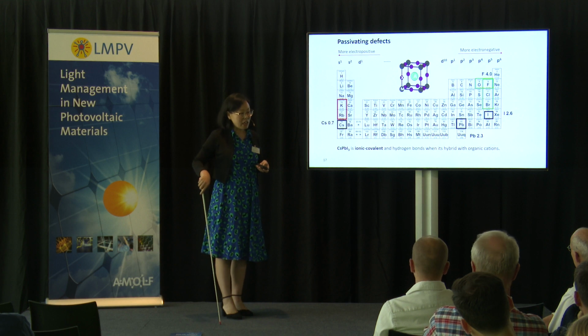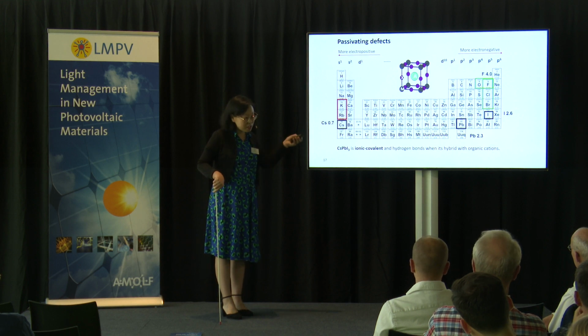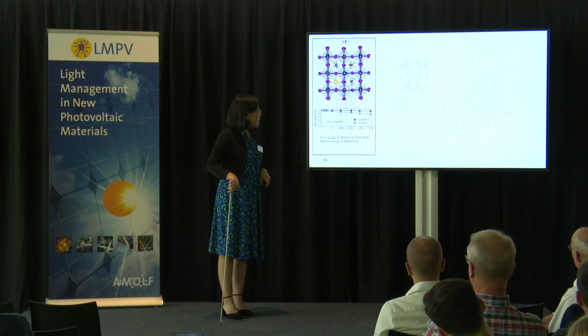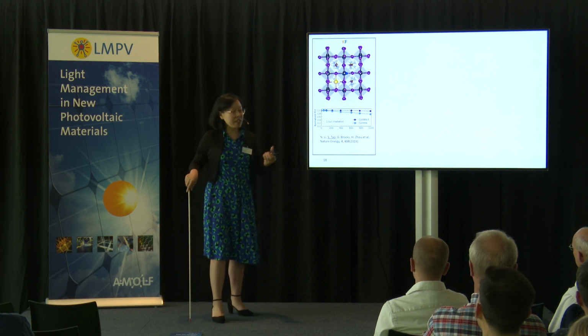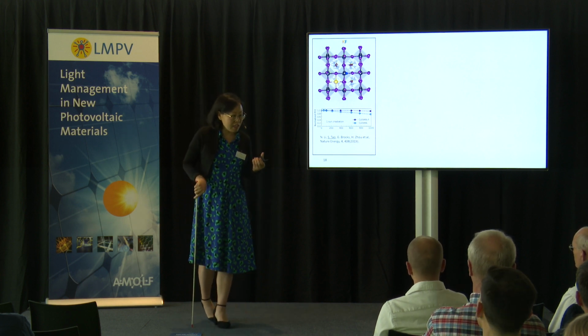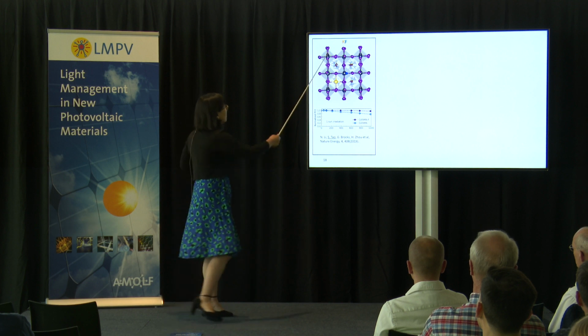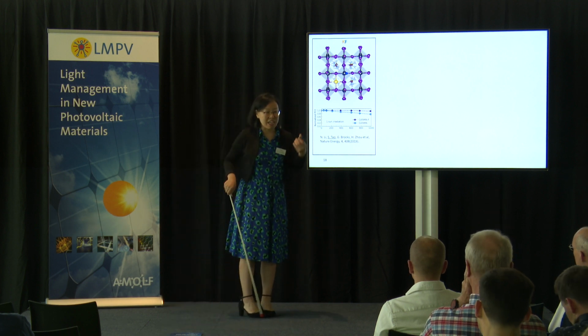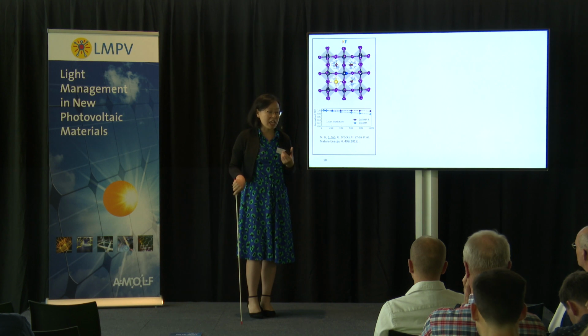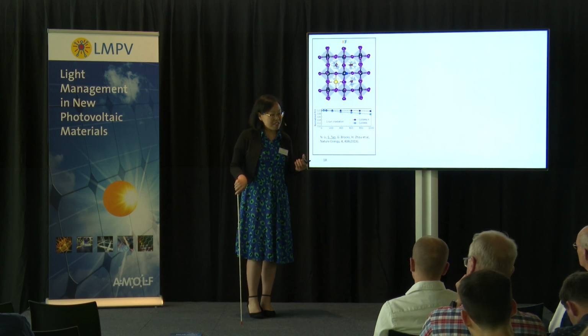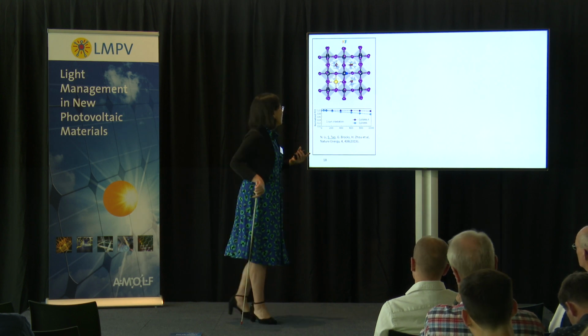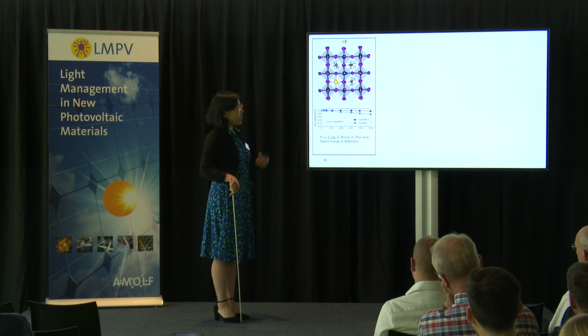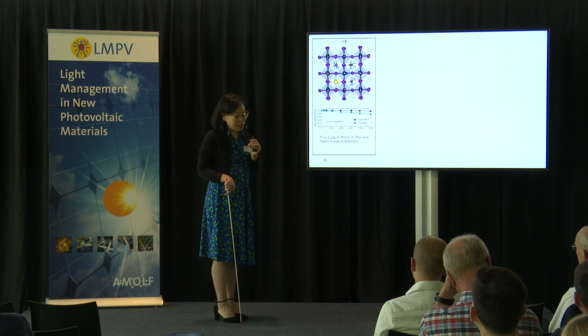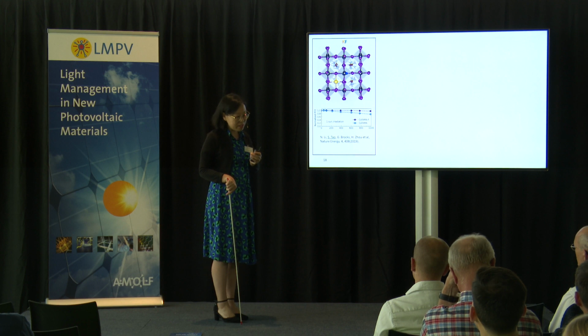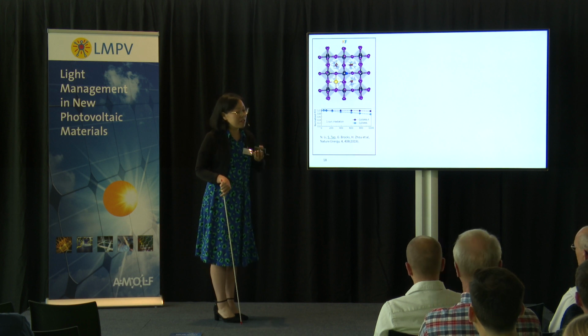And indeed, I'm going to show you a few examples of how we did this. The first case is incorporating a little bit of fluoride in the cells. Fluoride is the smallest atom, except hydrogen, of course, and has the most electronegativity, and therefore, when we make the cells, we put in a little bit of additive of this. Because it's small, it induces lattice strain inside, so it goes onto the surface.